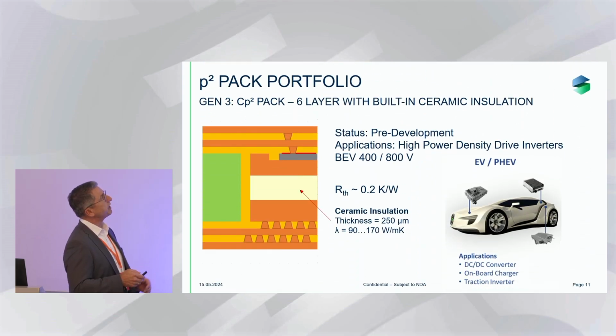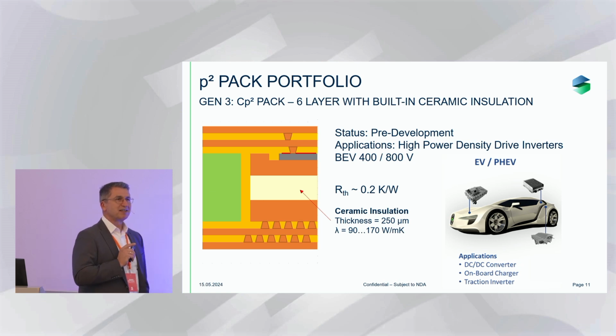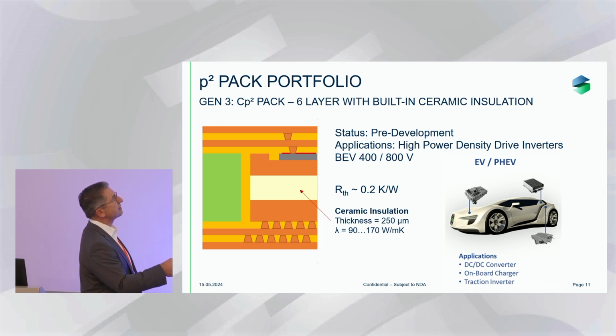And maybe we need to have the picture. So here we are, between the yellow and the orange ones. I suppose that the technology on the top is the same technology. So this is a substrate you can buy from the market. This is a double-sided copper coated ceramic substrate, so you can purchase this from the market. What we do is create this cavity and do the die assembly in the cavity. And then place it inside an opening of the inner layer, do a lamination process of the next layers, and do the interconnection with the microvias from the top and from the bottom.